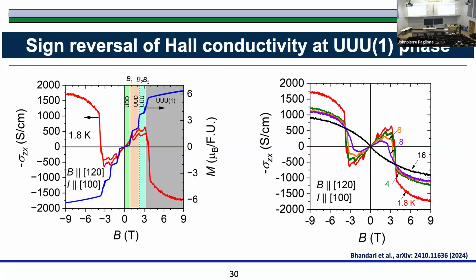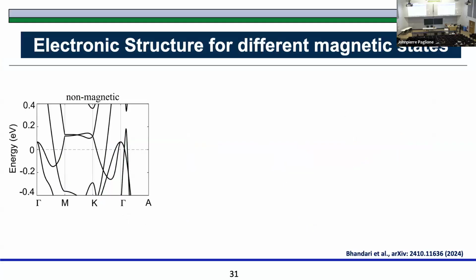And you see between 4 Kelvin and 1 point something Kelvin, there is a significant change. I don't have a proof, but what I think is that this may be related to the formation of something coming from the Dirac points in the system. The reason I'm telling you is that this is the band structure calculated in the non-magnetic state. It has this Dirac point here slightly above the Fermi energy in that state.